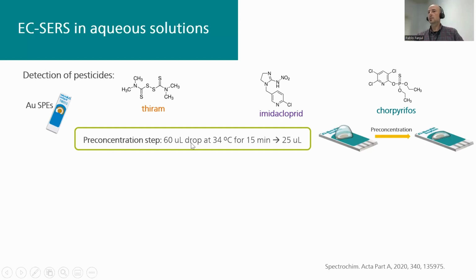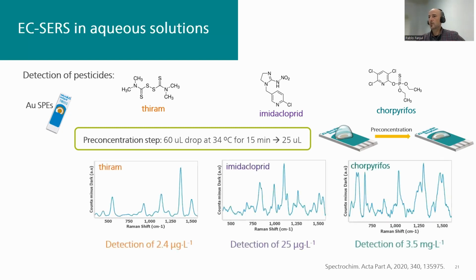In this case, we added first a small pre-concentration step, just reducing the volume of the drop of solution on top of our electrode. And with this process, we were able to get detection limits below the legal limits referenced by the European Union. So for the thiram, we are at 2.4 ppb, imidacloprid 25 ppb, and chlorpyrifos 3.5 ppm.